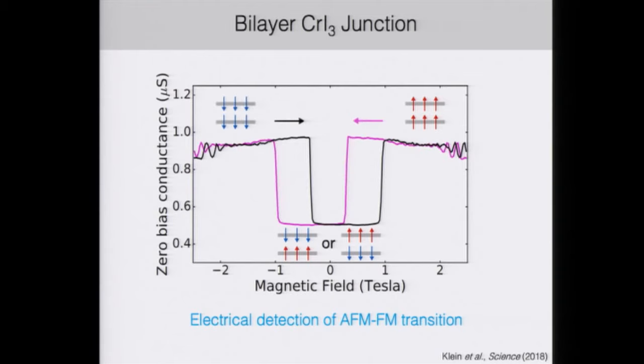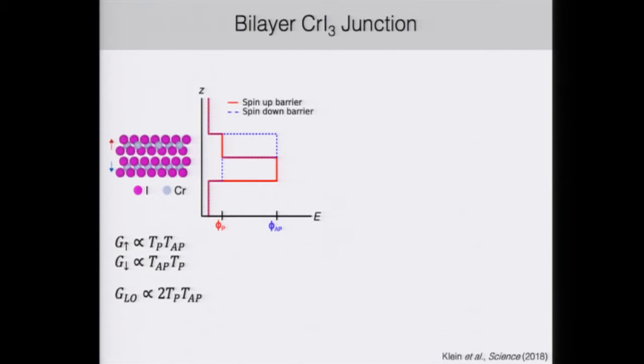And as we sweep the field in the opposite direction, we see similar results. We can try to understand this magnetoresistance by looking at a simple double spin filter picture. So in the antiferromagnetic ground state, both spin up and spin down electrons have to tunnel through a tall and small barrier, and this leads to overall low conductance or high resistance.